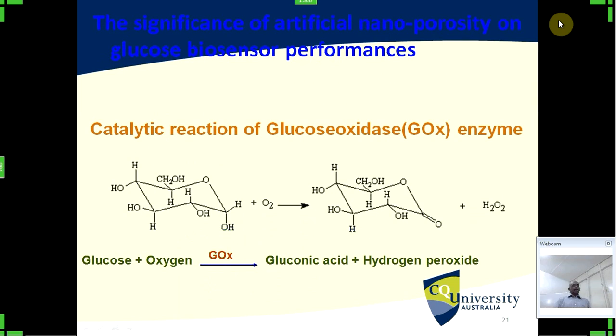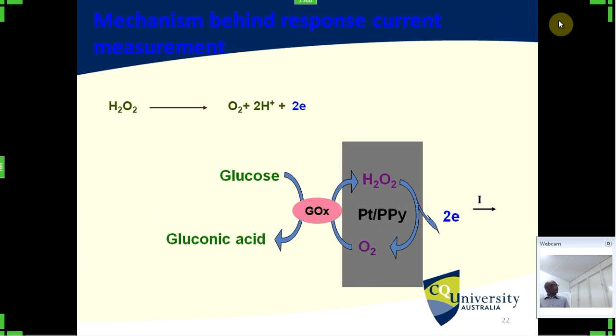And this is what happens when you have glucose, and when you have oxygen and glucose oxidase there, it makes gluconic acid and hydrogen peroxide. If you have more glucose oxidase, you can get a higher current here, because of the two electrons coming out from this reaction, we collect them and measure it as the current. So there are a couple of ways to improve the current or get higher sensitivity. One is improving the amount of glucose oxidase or improving the size of the sensor.